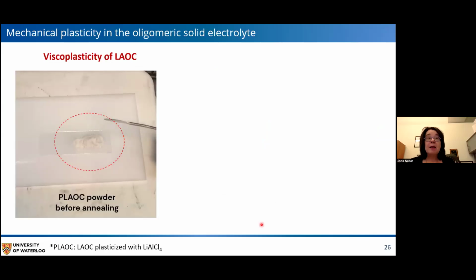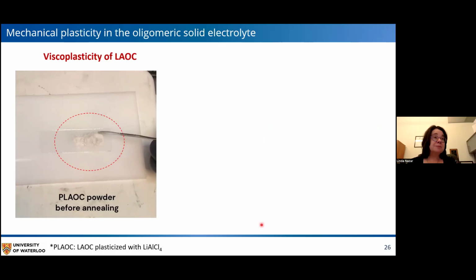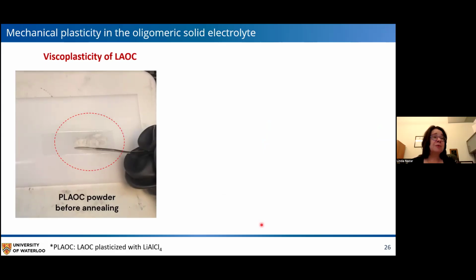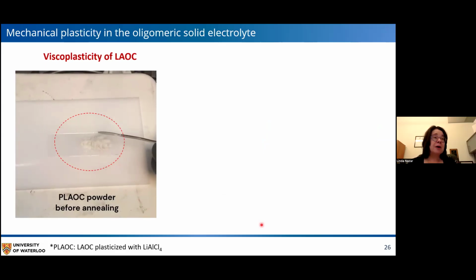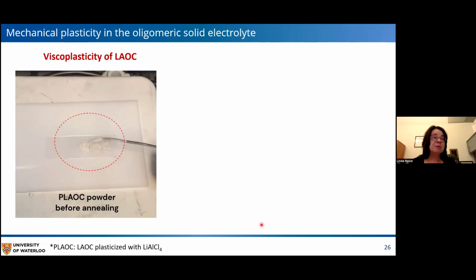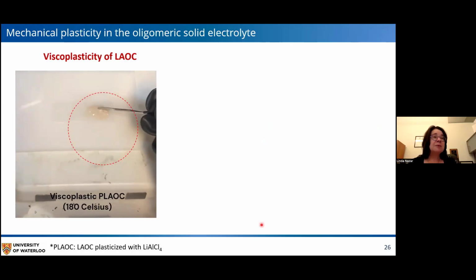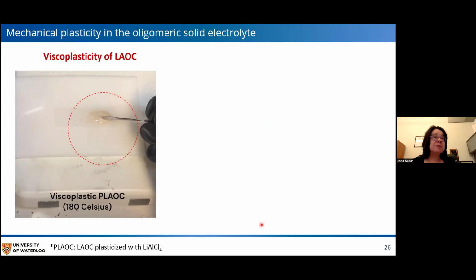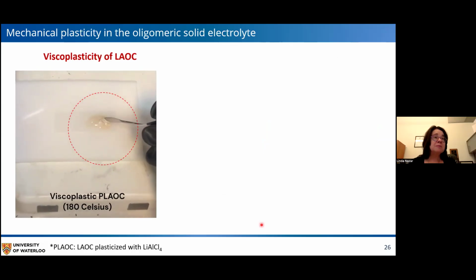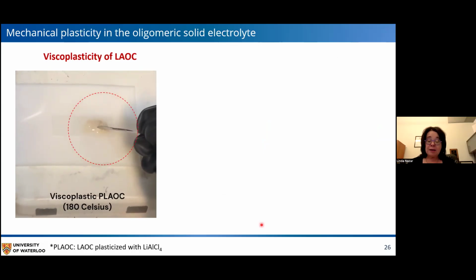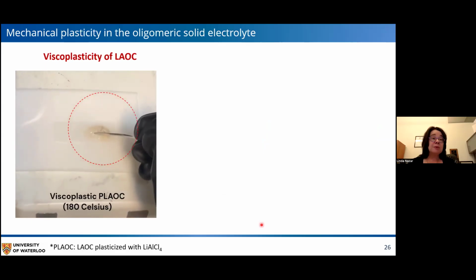And this plasticity can be seen here. This is a material before; the P stands for plasticized. We add a little lithium aluminum chloride to plasticize. And you can see that when you heat it at 180, it becomes a sticky, gooey material. And this is absolutely viscoplastic, not viscoelastic.